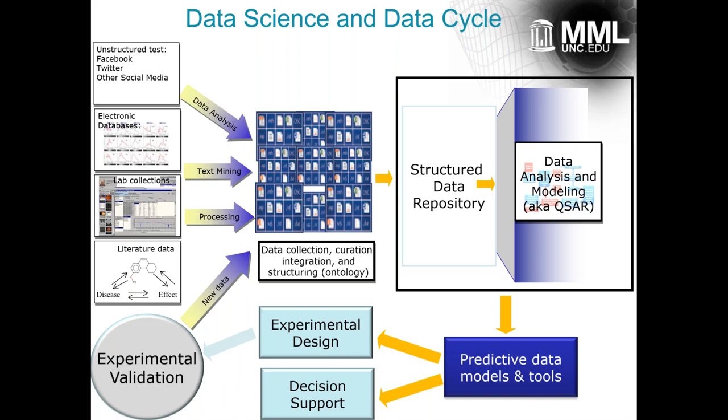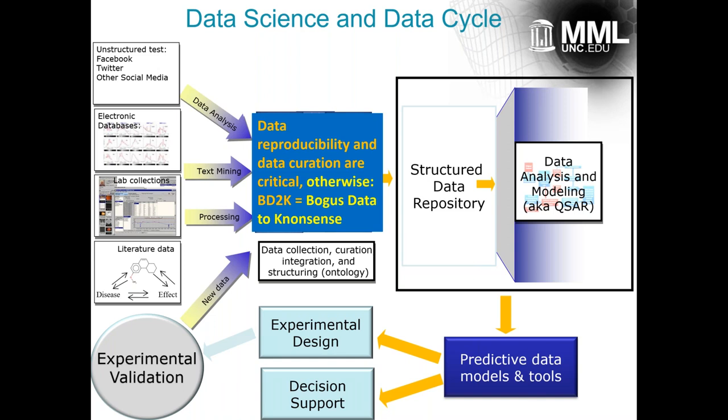For instance, the measured property often depends not only on the structure of the compound that we have available, but also experimental conditions under which the target property has been measured. And so if you're mindful of the sources of the data and if you're looking at experimental conditions, you may realize that you need to modify and adjust modeling procedures and start using not only structural descriptors of the compounds you're interested in, but also experimental conditions as additional descriptors. And so all of this is critically important in order to achieve the statistical accuracy of models.